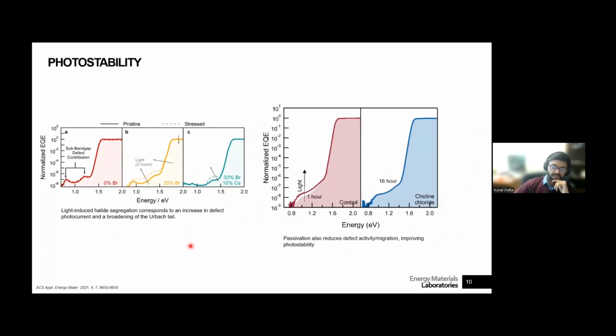The photostability is also affected. For example, this is a paper that we had previously published where we had looked at mixed halide perovskite solar cells and measured the defect photocurrent in these materials. So for example, this is the wide bandgap material for 33% bromide, so around 1.74 eV. And you can see that these undergo light-induced halide segregation. So this dark spectrum is of a pristine sample. And after shining light on it, you can see that this photocurrent contribution increases, and also this Urbach tail starts to shallow a little bit. So that's an indication of making iodine-rich phases in this material, which at the end start to affect the JSC of your devices because they act as kind of traps. And so we use this technique to characterize our now passivated material.